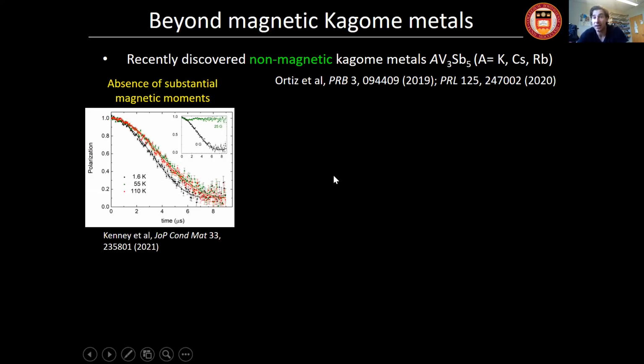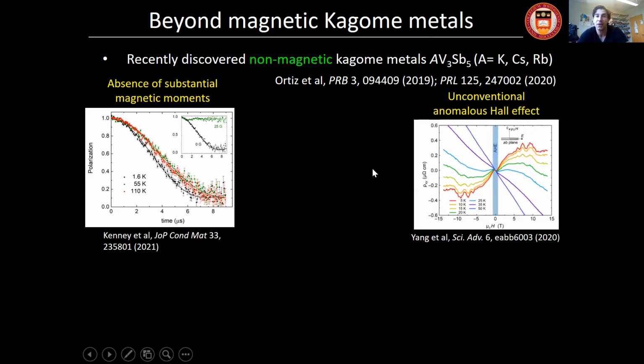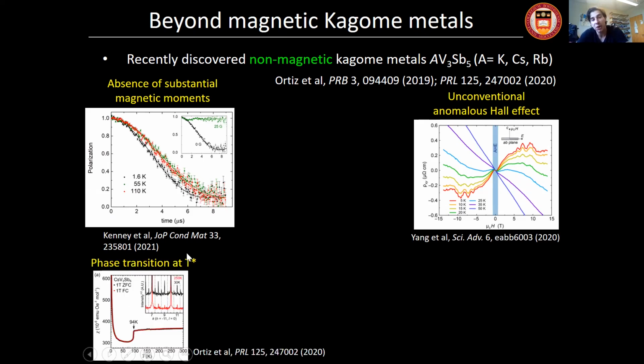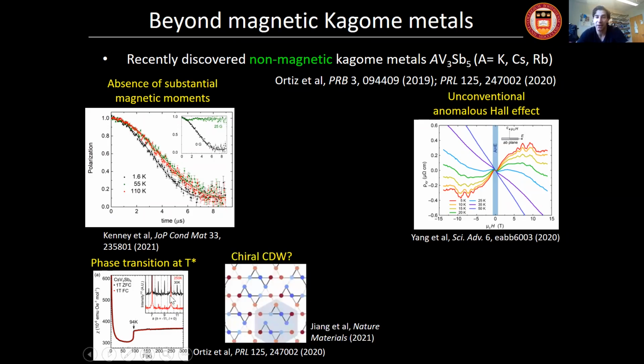So these materials are indeed non-magnetic, very different than iron tin, cobalt tin sulfide, and so on. They exhibit this unconventional anomalous Hall effect, which was very peculiar at the time, but also this interesting phase transition at about 90 or so Kelvin. This was later shown to entail a charge density wave, so a rare occurrence of a charge density wave in a Kagome system that potentially has this chiral character.